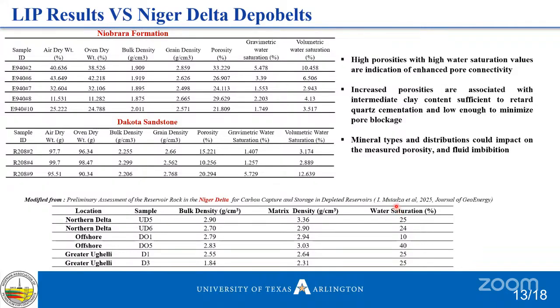But in terms of comparison with these studies, I found out that the samples I had were cleaned and oven dried, implying that what we have is just the pores, which is close to 100% because after cleaning and several hours of drying, I don't think there is still any other fluid in there. So when compared with the Niger Delta, this area is more tight. Niger Delta has a better reservoir properties, and that is why some of the reservoirs are considered as unconventionals in the basin.